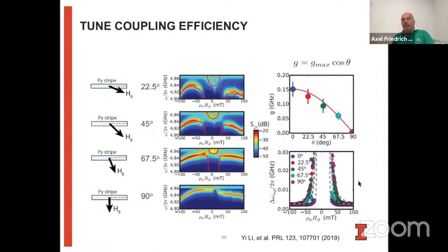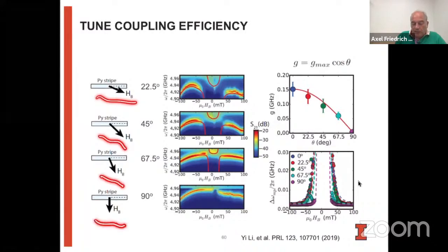Now, I was saying earlier that one of the beauties of using magnon systems in these coherent information processing things is that we can modulate the coupling at will. And one way we can do this is by simply changing the orientation of the magnetic field with respect to our stripe. The reason is the RF resonance field is always perpendicular to the stripe, the way the stripe is integrated in the resonator. And so if we align the magnetization perpendicular to the stripe, then there is no coupling between the magnetization and the RF field anymore.